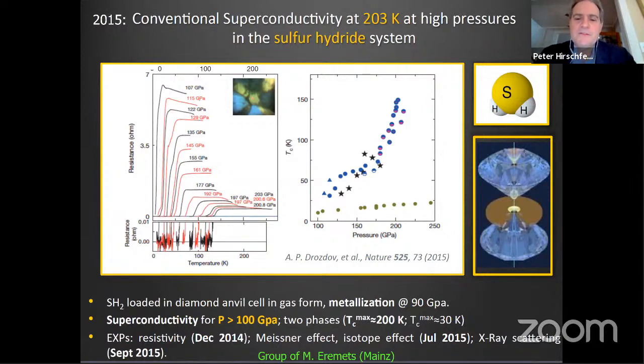But in 2015, Mikhail Eremets in Mainz discovered that when he put hydrogen and sulfur under pressure, he started with H2S gas. When he put them under pressure in a diamond anvil cell, took them up to 200 gigapascals, he found superconductivity above 100 and a maximum critical temperature of 200 Kelvin. Now that's higher than anything I've shown you so far, and was unexpected, let's say, to at least many of us in the community. Not to everyone, but to many of us. And he showed the existence of the Meissner effect, the isotope effect. It looked, roughly speaking, like an ordinary conventional BCS superconductor that's created only under very high pressure.